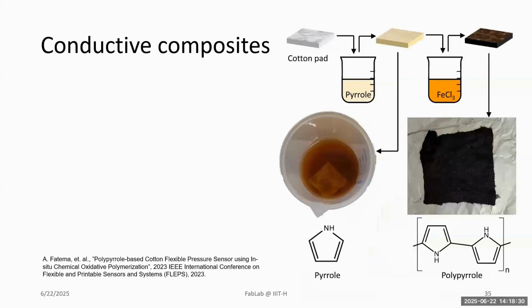Now, once we have all of this in place, it's time to do some experiments. One of the things that we do in my lab is to create polypyrrole structures, and one of the interesting things about it is that you can actually create these structures almost anywhere you want, right? We do it using what's called in situ chemical oxidative polymerization, in which, for example, you can take the pyrrole monomer solution, take a cotton pad, dip it in a pyrrole solution, and as soon as you expose it to FeCl3, for example, FeCl3 oxidizes the pyrrole and gives it the sites for polymerization. And once that polymerization is complete, you will get basically that black